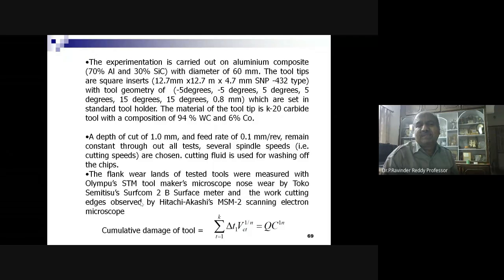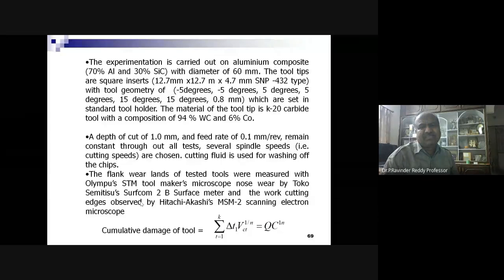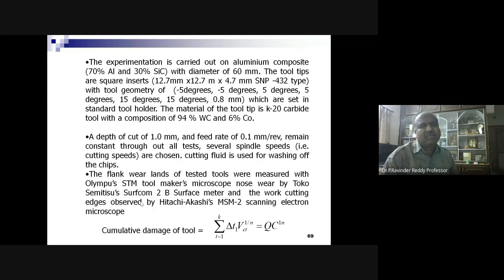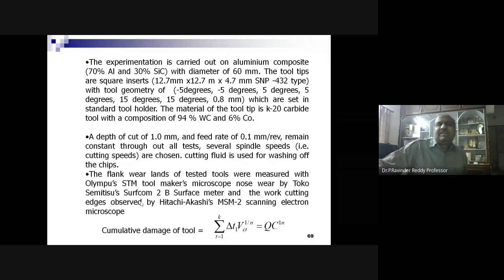So here we conducted experimentation on aluminum composite with 70% aluminum and 30% silicon carbide with a diameter of 60 mm. The tool tips are square inserts, 12.7 by 12.7 mm and 4.7 mm, SNMG 432 type, with a tool geometry of 5 degrees, 5 degrees, minus 5 degrees, plus 15 degrees and 0.8 mm, which are set in a standard tool holder. The material of the tool tip is K20 carbide with a composition of 94% WC and 6% cobalt.